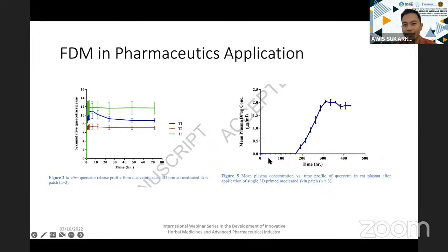And then this one actually they tested the patch on the rat. So when they put the patch on the rat, at first, before the 200 hours, they couldn't detect any active ingredient or the quercetin in the rat plasma. But after the 200 hours, they start to see an increment of the quercetin in the rat plasma. So it means the patch managed to penetrate the skin and then enter the body system of the rat. And you can see it's maxed out around 300 hours here.